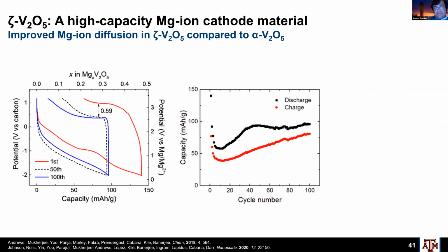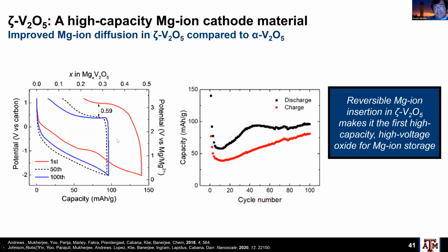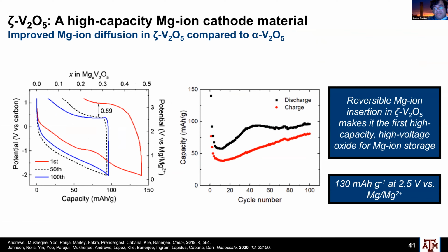And here's some cycling data on magnesiation. And working with Jordi Cabana's group, we've also made nanoparticles of this that actually do a little bit better for capacity at higher temperatures.